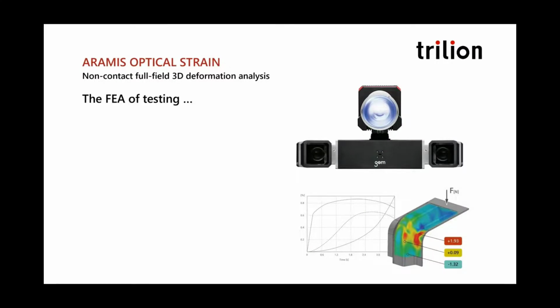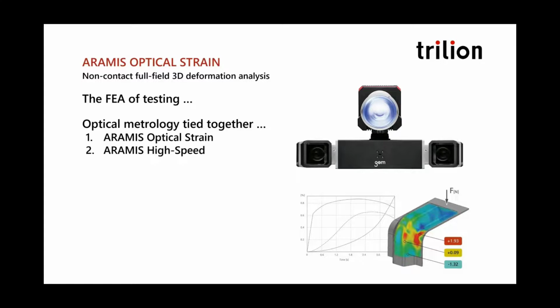So Aramis optical strain is, again, called the FEA of testing for good reason. But all our optical metrology tools are really just tied together. We have our Aramis optical strain. We have high-speed data that we work with. We have a whole webinar about that tomorrow. The Aramis thermography adds this whole other layer of thermal mapping to the deformations and strains that we're measuring with Aramis, and allows us to correct the strains for thermal expansion to get the true mechanical strains in high temperature environments like the B-2 bomber.